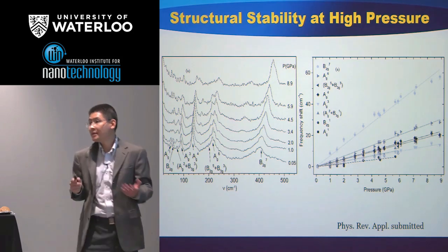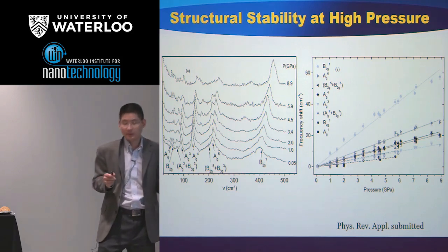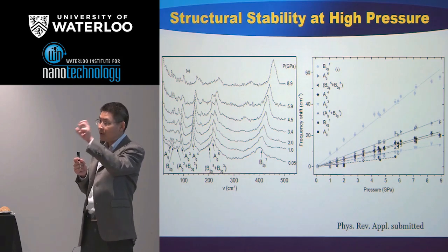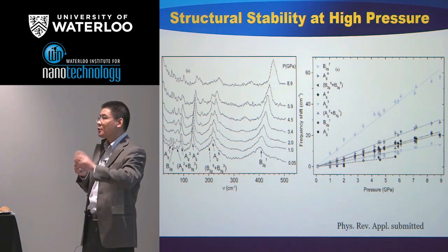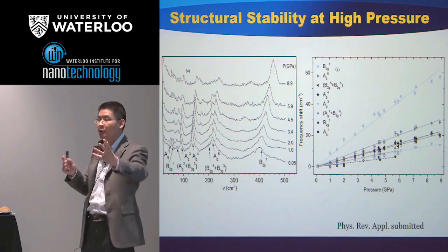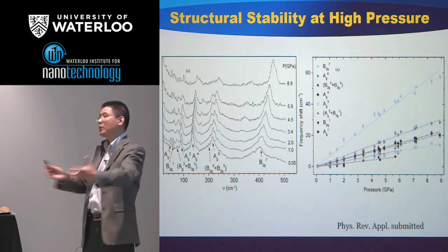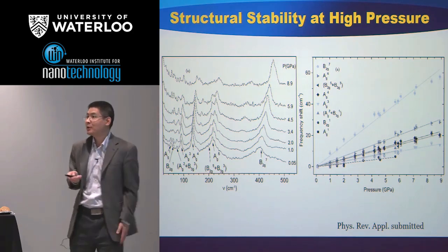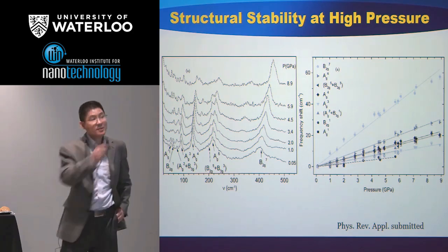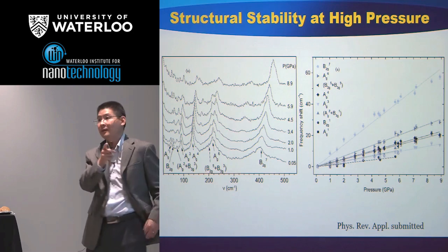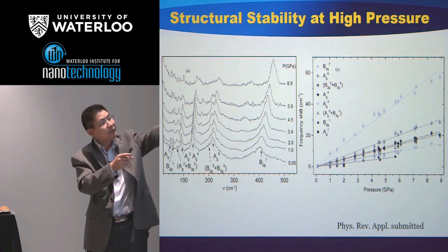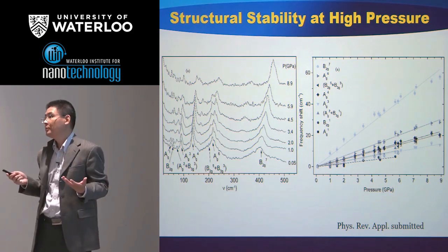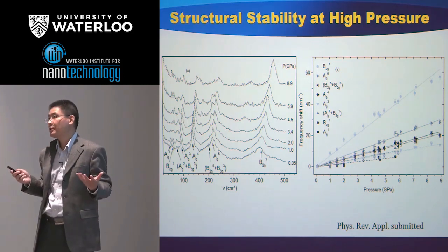Okay? Why is it important? Well, because titanium actually has a smaller atomic radius, right? So by doping titanium to replace zirconium, you are actually applying a chemical pressure. It's effectively like applying external pressure, right? So this way, we have demonstrated that, at least from this point of view, incorporating a large amount of titanium is possible without changing its structure.